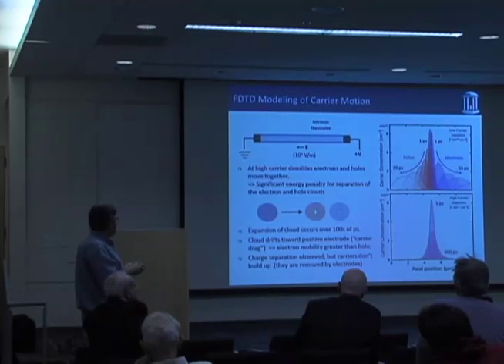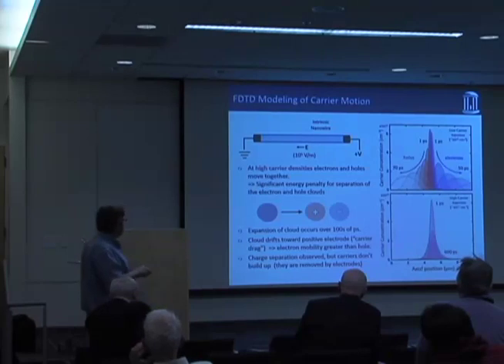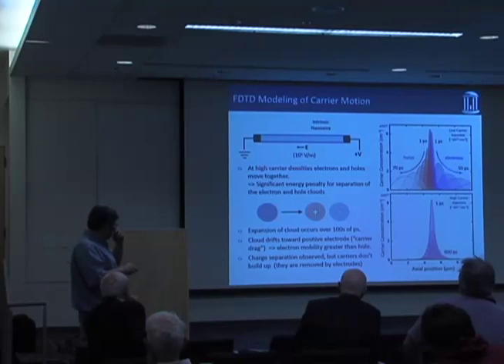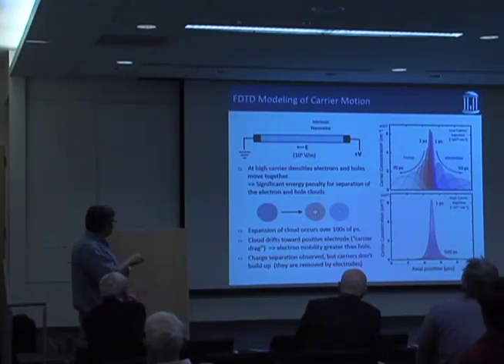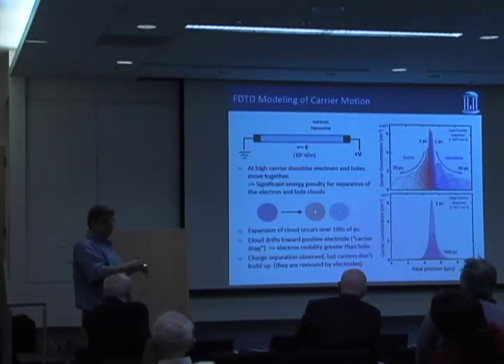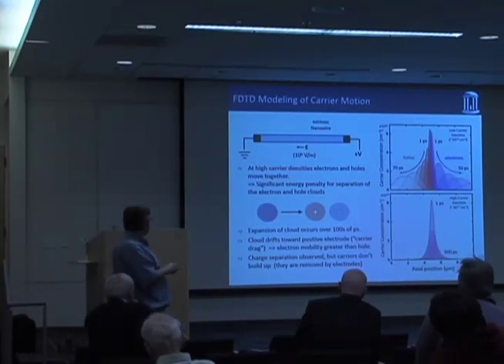Okay, and the reason why you don't see charge separation is because you have a whole bunch of electrons, you have a whole bunch of holes, and it takes energy to pull them apart. And that carrier density is too high, and the field in sort of the junction is too weak to overcome that. And so you actually don't see charge separation until the carrier density through recombination decays to a point that's below a threshold, and then you'll see it. And in fact, in these simulations, you'll see charge separation way out in the wings of the distribution where the density is really low.